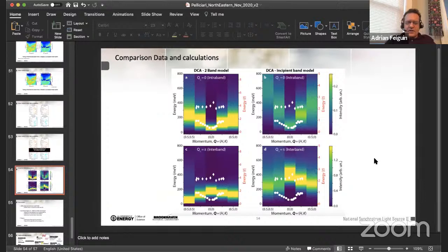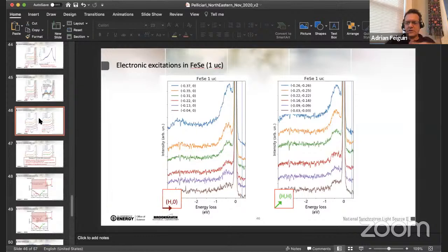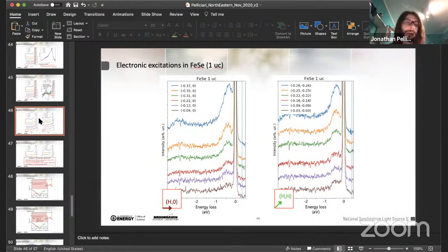Yes. When you show your data, you focus on a window of about 1 electron volt, and the spin excitations within this window. Imagine you had a Mott insulator with a gap of 2 or 3 eV, for instance. Can you look at the excitations on the upper Hubbard band or not? How high in energy can you go? Well, in soft X-ray RIXS, we can go up to 10, 12 eV. It's pretty common to observe charge transfer excitations, for example in cuprates and nickelates, up to 5 eV. It's a pretty broad featureless peak. We are able to see crystal field excitations between 1 and 3 eV and easily up to 7, 8, 10 eV in one single shot.